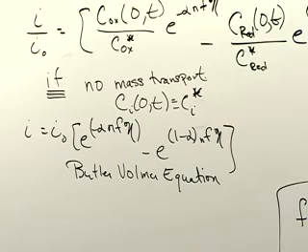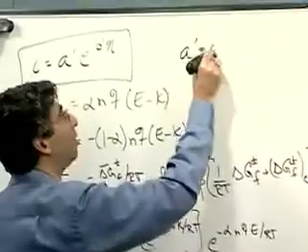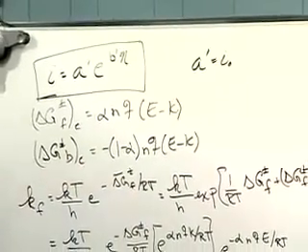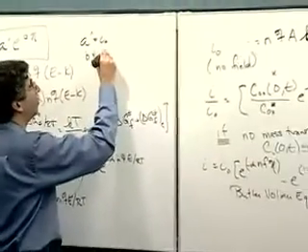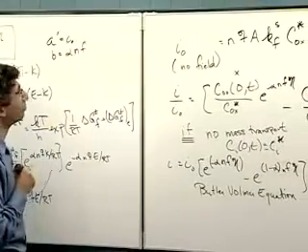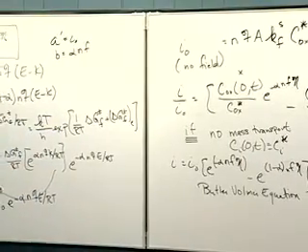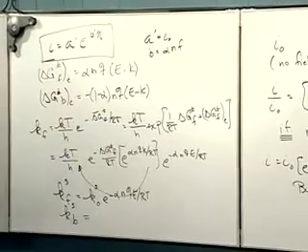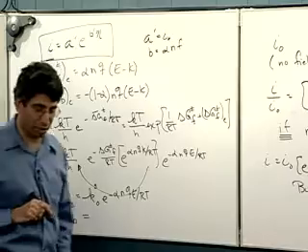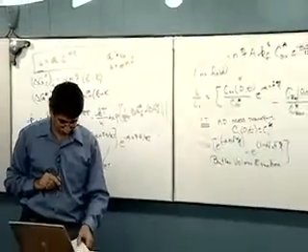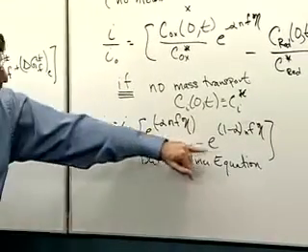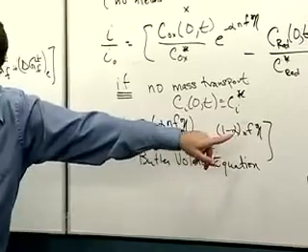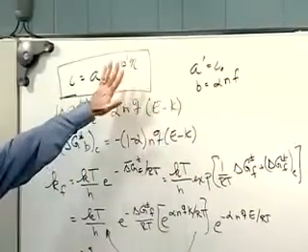And you'll notice that if I go back and simply identify A prime, like I did very early on, with this term I naught, and identify now B with these things like alpha n times this little f, that is the temperature and symmetry factors in this, then the Butler-Volmer equation and the Tafel equation are the same thing. In particular, in this one I'm allowing both a forward reaction and a backward reaction to occur. In this one, I only have the forward reaction occurring.